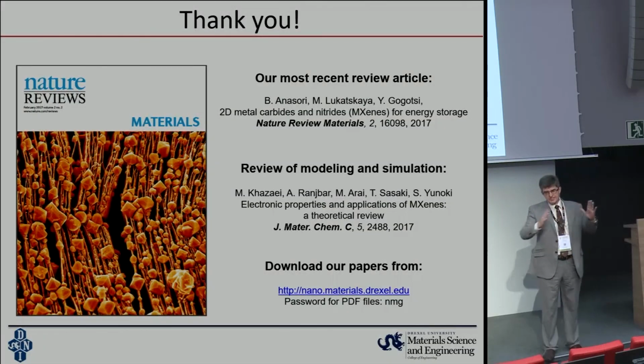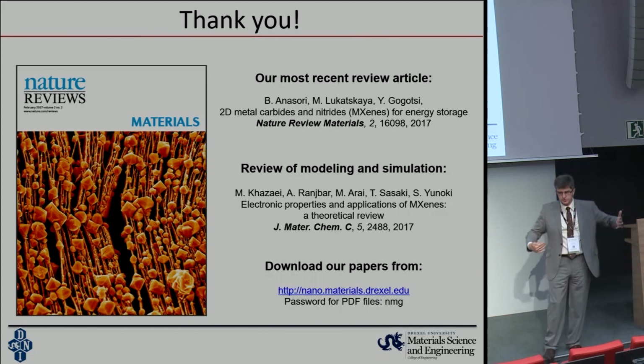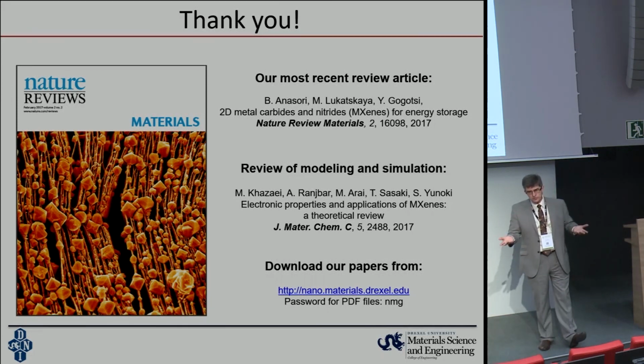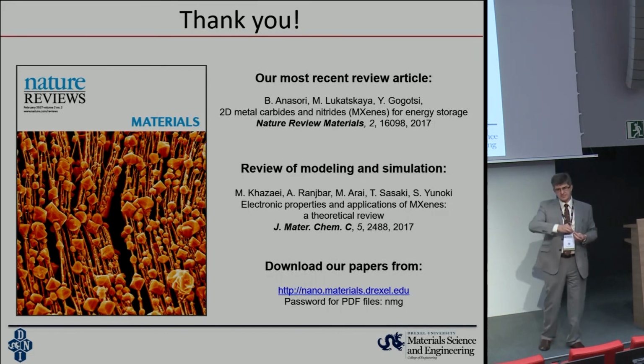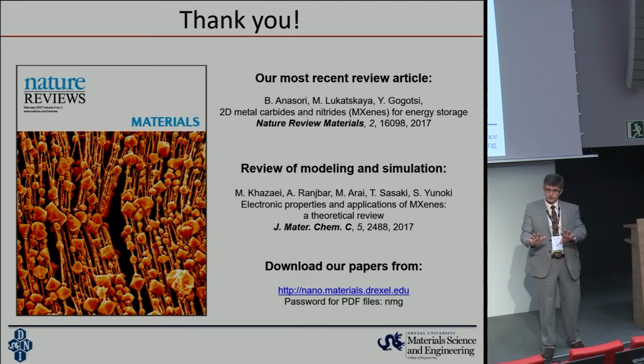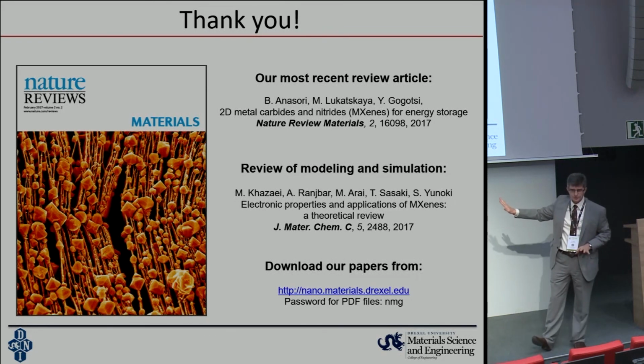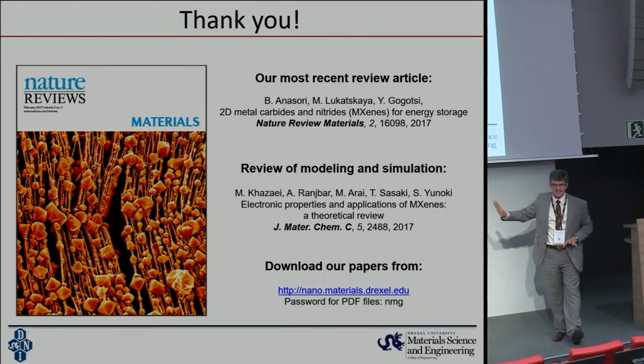We basically work a lot in architecture. And this work I showed at the end, for example, with liquid crystal alignment, is a kind of this work. We can also make it more disordered. Just like clays, we can also pillar them by introducing large organic molecules between the layers. For example, you can use diamines, which will attach electrostatically by positively charged amino groups to the surface here. Or you can introduce, for example, tertiary amines with different length hydrocarbon chains, and open spacing. So pretty much everything you know for clays can be applied to those materials. Consider them to be metallically conducting clays.